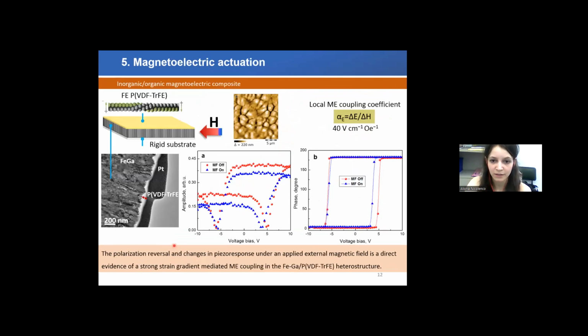We also tried to demonstrate the proof of principle of magnetoelectric actuation, that we can indeed induce some strain in these nanoporous iron gallium films, and that this strain can be transferred to a second phase material. To do that, we coated our electrodeposited nanoporous iron gallium films with the polymer PVDF-TrFE. This is a polymer that has some piezoelectric properties, so it can induce some charges on its surface when it is strained. This is the topography image of the polymer obtained using piezoresponse force microscopy. We can see that the shape actually repeats the grain structure of the iron gallium, and we can see these kind of spaces between the grains.